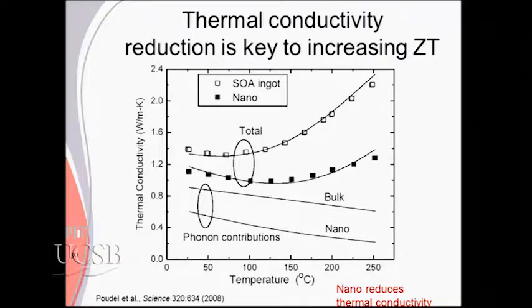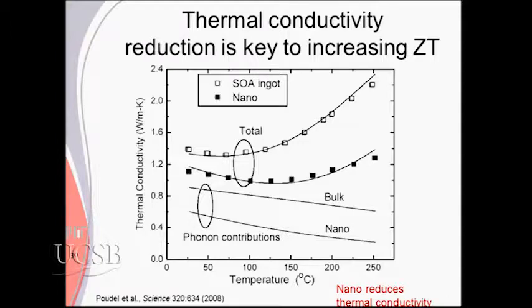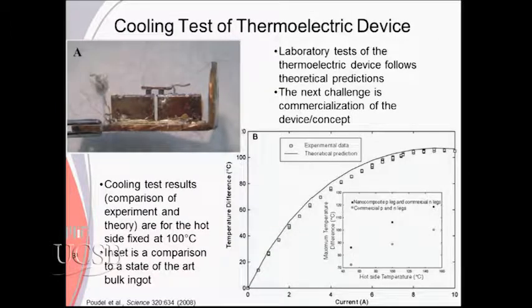The nano part of the lattice was the phonons that were the biggest effect. That's what we show with this. So this is for the totals, and this is now just the phonon contribution, and that was the most important individual part. So we understand a little bit about the science and where we're heading and somewhat why we're heading in that direction. Now, thermoelectricity is a very strange kind of field.